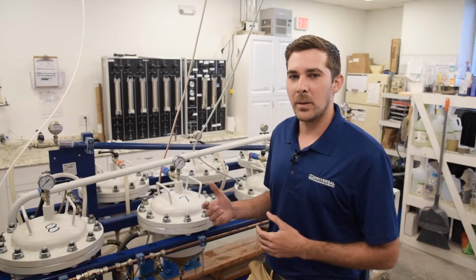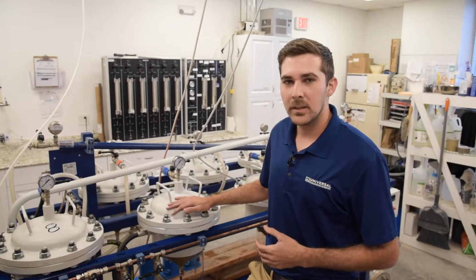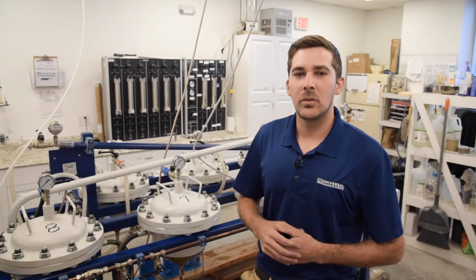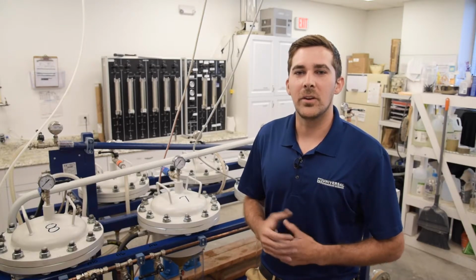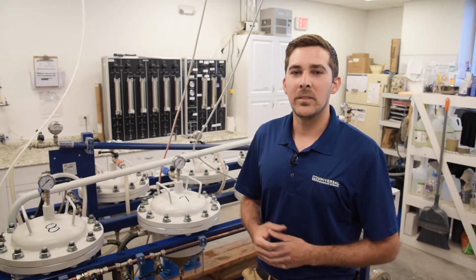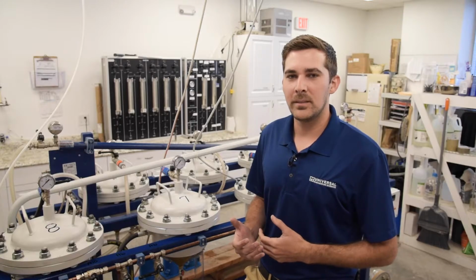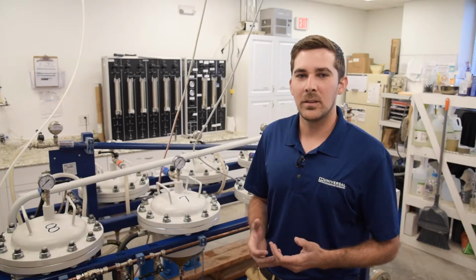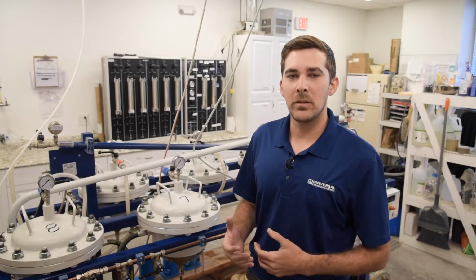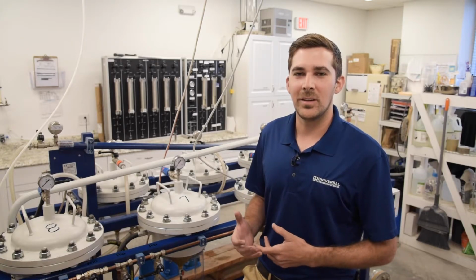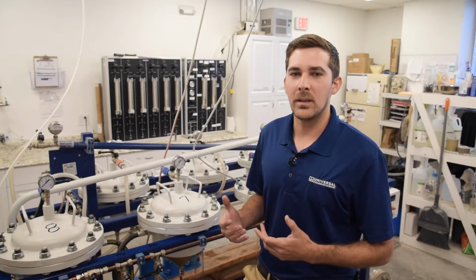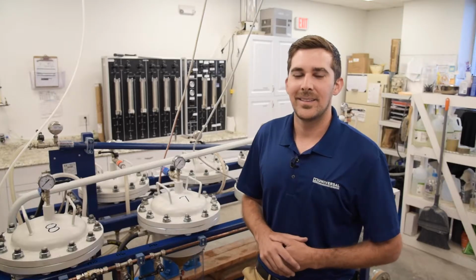Once the specimen and chamber are confirmed to be watertight, the water pressure is increased to 200 psi for the duration of the test. We have seen tests completed within 3 weeks and last as long as 3 months, which is all dependent on admixtures, water to cement ratio, and other variables within the concrete's mix design.